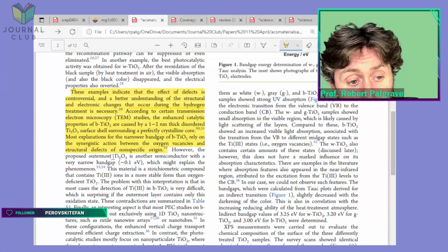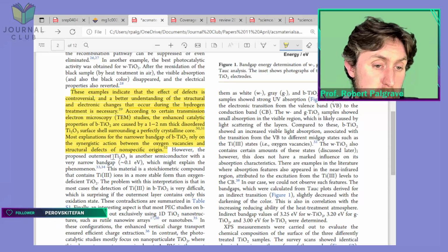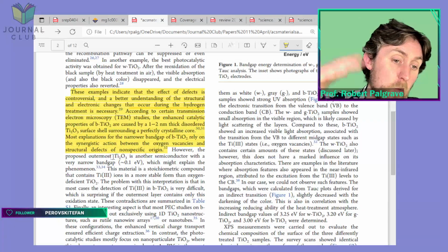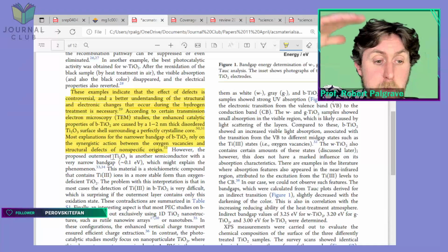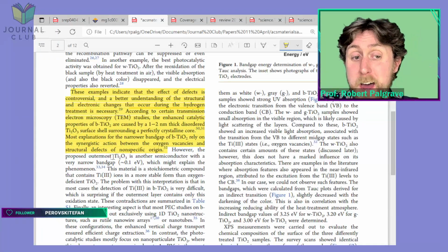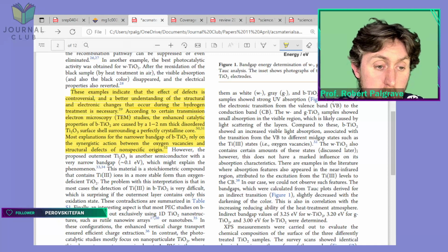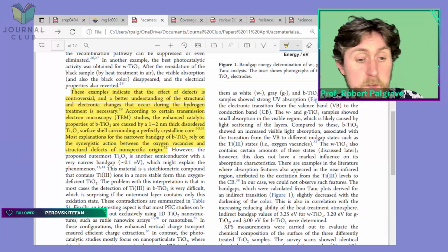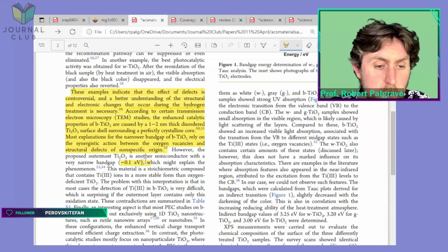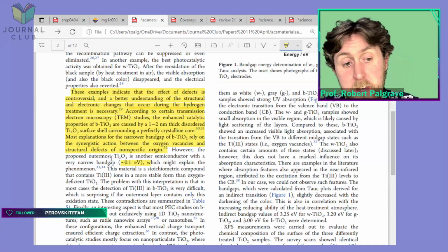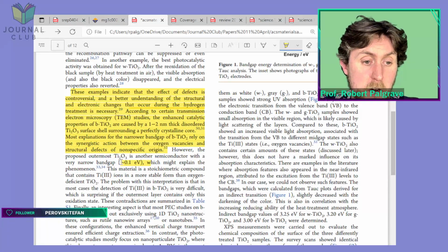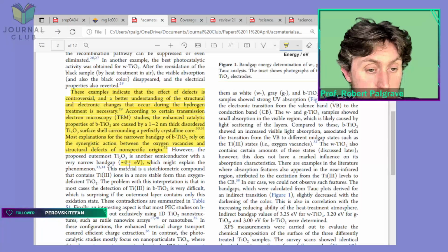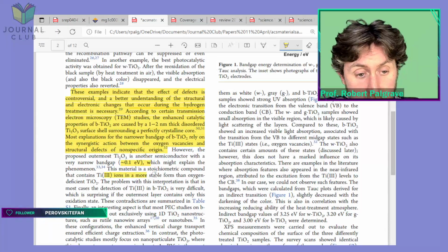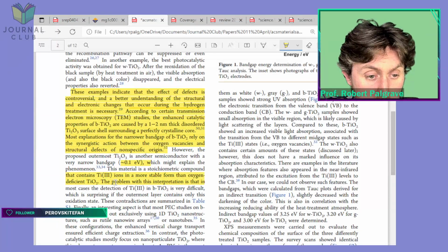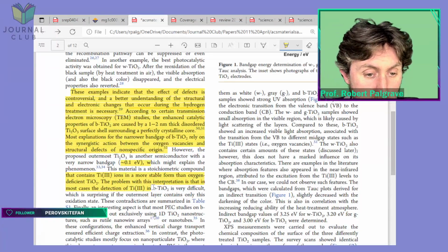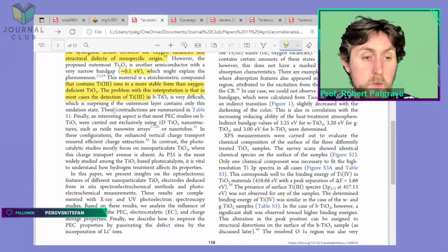It behaves very differently, especially in its interaction with light. So that one electron in a d orbital can easily be moved around. In fact, it's in a d band, so it behaves more like a metal, with a very, very narrow band gap of 0.1 electron volts. 0.1 electron volts. So it could be this Ti2O3 region is the cause of the black colour. This material is a stoichiometric compound. Okay, this is what I just said. Contains Ti3+ in a more stable form than oxygen deficient TiO2. Okay, stability is always debatable, but you could always ask under what conditions.